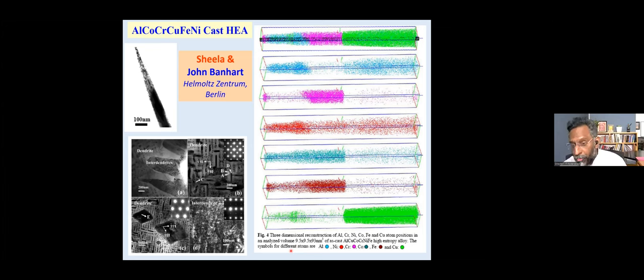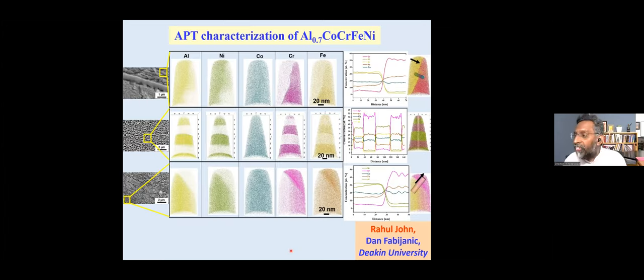Now, we can also see if you have two phases inside such an alloy, what is the composition of one phase, and what is the composition of the other phase. All these colors that you see are indicative of what elements are present. Which element is getting segregated to which phase? All this can be easily seen at the atomic level. This is something very, very fascinating when you actually use them.